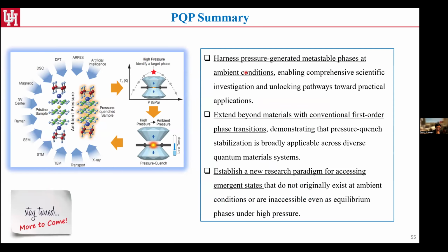So I think based on our recent results on pressure quenching high TC superconductors, we proved that the pressure quench is a unique and nice approach for us to really get pressure-generated metastable phases at ambient condition. And it also goes beyond the materials that have those conventional first order phase transitions. So you can try a broad range of quantum materials.